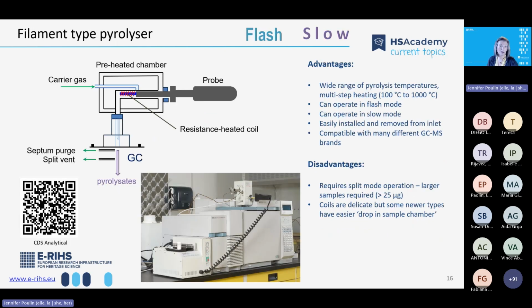The filament type pyrolyzer uses resistance to heat a sample tube with a platinum filament. So there's a lot of advantages to this. You have a wide range of pyrolysis temperatures, and you're also capable of doing multi-step heating. It can operate in flash mode, but you can also slow it down and operate in slow mode. It is pretty easy to install it and remove it from the inlet. So once you convert it to PyGCMS, you can take it off again and use the instrument in GCMS mode. And these are compatible with many different types of GCMS brands. It does require split mode operation. So we're looking at 25 micrograms, probably as the smallest sample. And I found in my use that the coils were pretty delicate. It was a little bit tricky sometimes to use. But some of the newer types have this drop-in sample chamber, which looks really great.